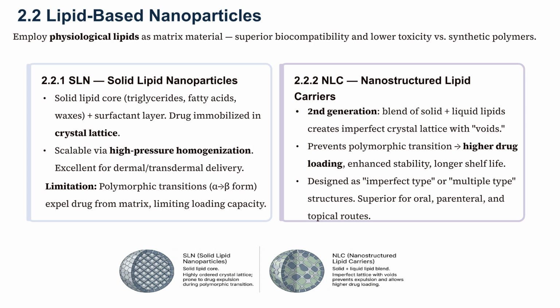Moving to lipid-based nanoparticles, these carriers use natural fats, offering much better biocompatibility and lower toxicity than synthetic plastics. The first generation, solid lipid nanoparticles, or SLNs, trap drugs inside a highly ordered solid crystal lattice. While great for skin delivery, this strict structure often squeezes the drug out over time. To solve this, scientists developed a second generation, nanostructured lipid carriers, NLCs. By blending solid and liquid lipids, they create an intentionally imperfect lattice filled with tiny voids, allowing for much higher drug loading and a much longer shelf life.